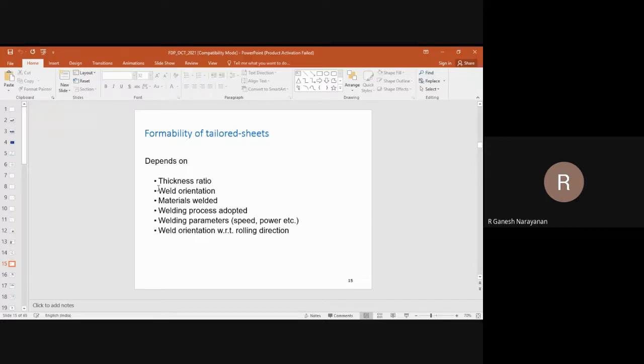Similarly, you can have strength ratio also. Then weld orientation comes into the picture. What is the orientation of the weld with respect to loading direction? Materials welded, that's what I told you, strength ratio. Welding process adopted: laser welding, friction stir welding, we will see some examples. Same material, same thickness, but what process you are going to adopt? Then welding parameters. Once you enter one welding process, there are several parameters. For laser welding, examples are speed, power, intensity. For friction stir welding, I will give you some examples; there are several parameters.